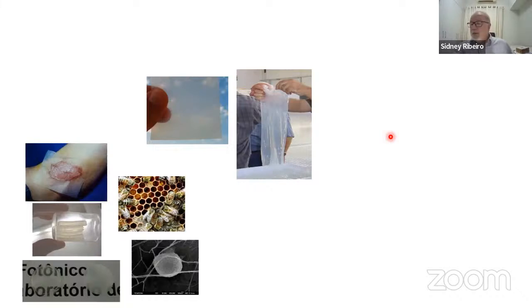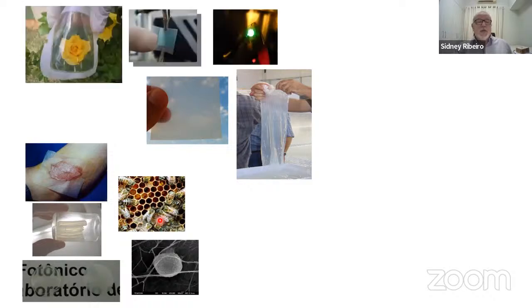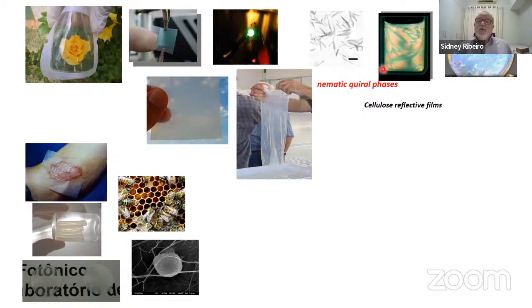I must run with the time. So we can make bandages to treat wounds, to replace the skin. We can make tubes, we can make ophthalmic lenses. You can incorporate propolis or silver nanoparticles in order to add the properties of these materials. You can obtain transparent substrates in order to prepare transparent OLEDs. You can hydrolyze cellulose in order to have cellulose whiskers that will self-assemble in solution above a critical concentration in order to give you nematic chiral phases.